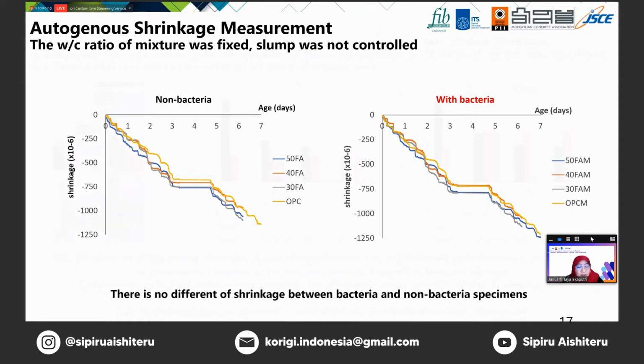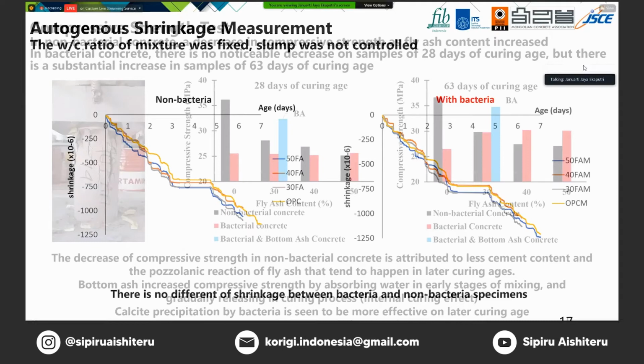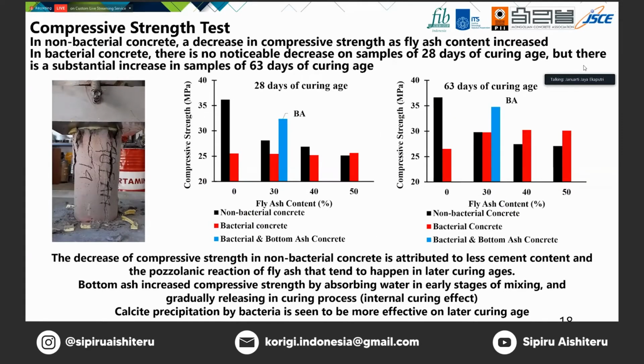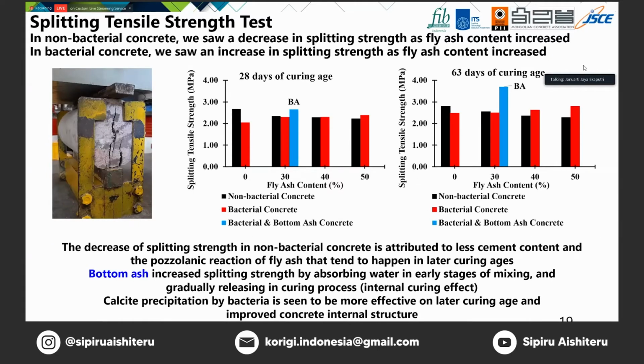For the compressive strength at 28 days, as expected, concrete with the higher fly ash content has lower compressive strength. However, at the later age, at 63 days, we found that the increasing rate of the strength is higher than the normal specimen. It is very pleasing to see that the effect of the internal curing by bottom ash worked very well, as the effect of the bacteria to fill the concrete pores during the hydration. And as expected, because of the denser concrete pores, a higher split tensile strength is shown by the specimen containing bacteria and bottom ash, as can be seen here in this result.